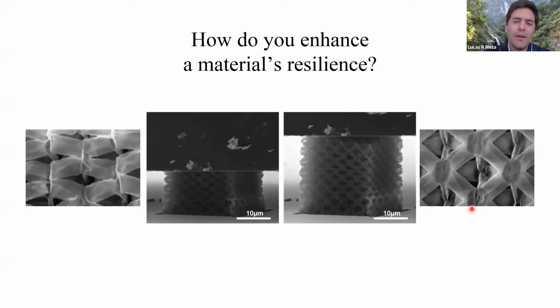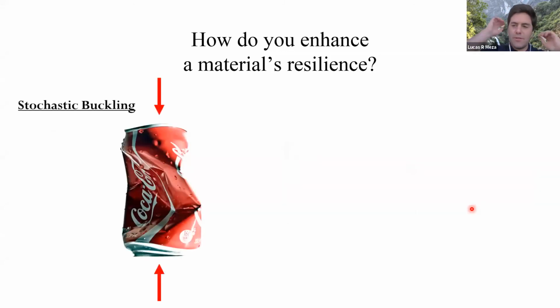This is inherently a buckling dominated process. You can think about this in the context of a soda can. If you step on a soda can, it'll buckle randomly and take on some random shape, ending up with sharp corners, sharp nodes. Those sharp corners will actually be failure nucleation points. You'll get holes that start to pop in here, which is particularly bad if you want to then unbuckle it and reuse it.